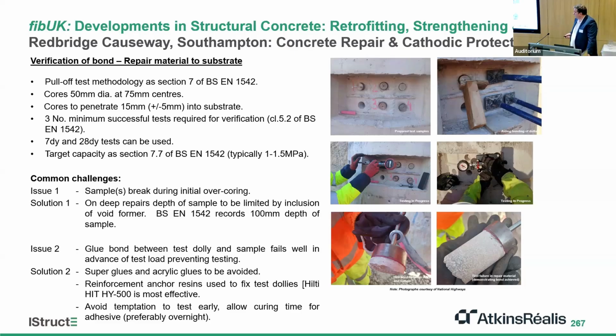So 1542 records a depth of 100mm. So what we've had to do, this is a recent scheme for National Highways where we've done this, we had to include a box out in the overlay to do the testing to make sure that the depth of sample wasn't too long, so it broke off during coring. The other issue that we frequently see on pull-off tests is the debonding of the test dolly from the sample.